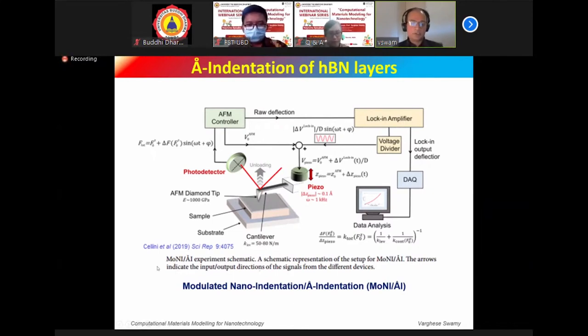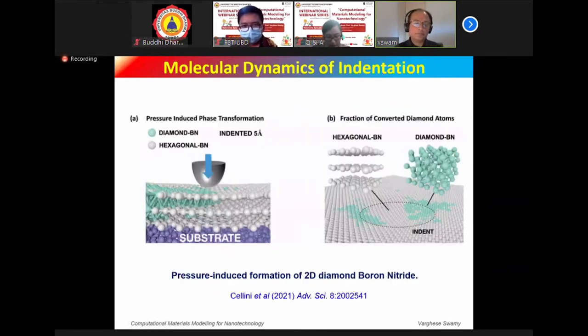So they have used this technique alongside some molecular dynamic simulation to study what might happen. And the molecular dynamic simulation setup is shown here. They have created an equivalent molecular dynamic simulation setup where they have the silica, SiO2, substrate, which is modeled using some interatomic potential. I can't recall the details. You can look at this paper. It's just published in 2021, above which they have different layers of hBN, 1, 2, 3 layer case here.